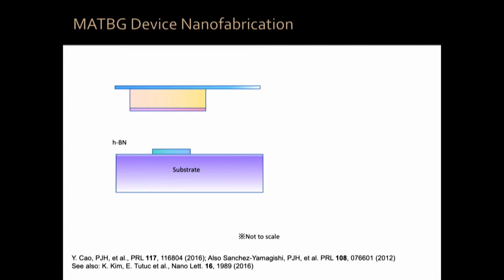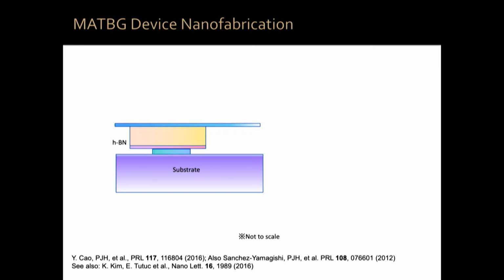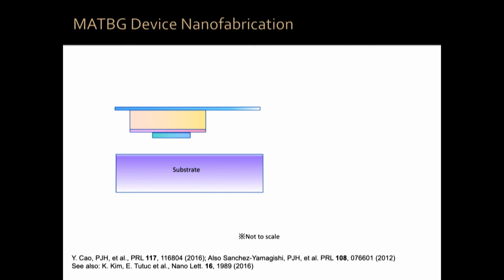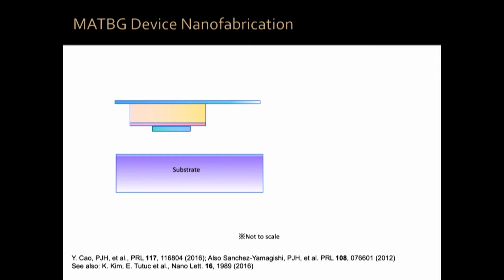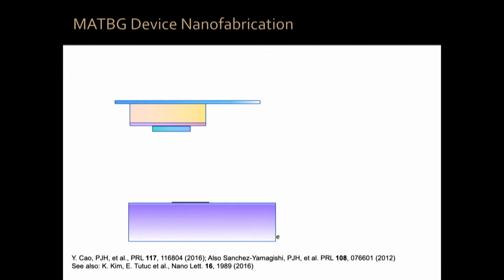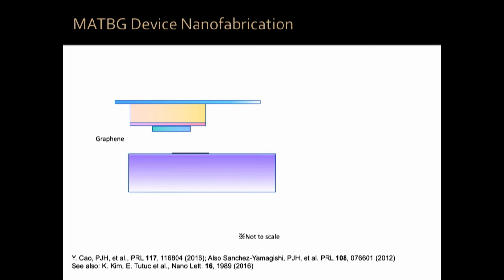For the purpose of the first part of my talk, it's just a high quality dielectric, insulating material for graphene to sit on top. That's the purpose, okay? So we come with our sticky polymer and we pick up the hexagonal boron nitride from the substrate. Then we bring another substrate which has monolayer graphene sitting on top of it, okay?